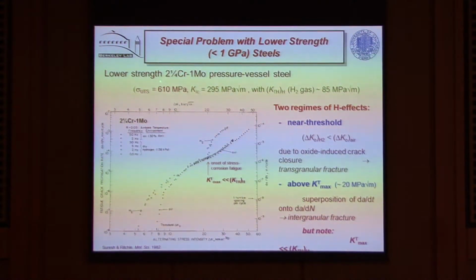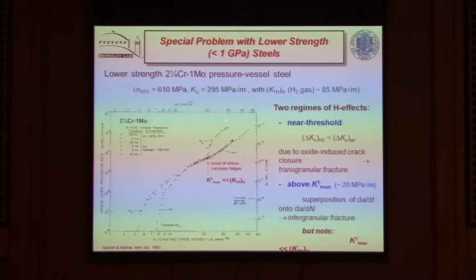In this particular material, this is a lower strength 2¼ chrome moly steel, the stress corrosion, or the sustained loading threshold in hydrogen is at 85 megapascal root meters. It's about here. So many people have thought, okay, these steels are relatively immune to hydrogen embrittlement. If I have stress intensities below this level up here, I haven't got to worry. But if you do those experiments in fatigue, and most structures see cyclic loading, lo and behold, you get this same effect, this sudden acceleration, but at much lower levels than the stress corrosion, than the sustained load cracking. If you did the test under non-cyclic conditions, you'd have to have a K up here before you see hydrogen embrittlement, but under cyclic loading, it occurs at much lower levels.